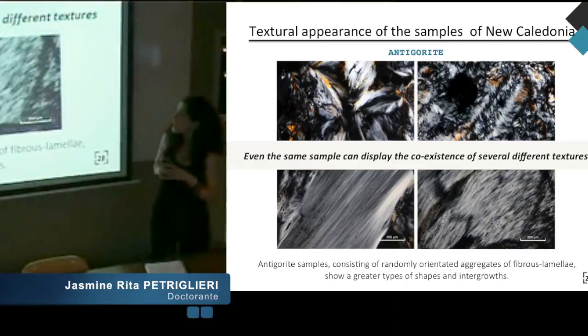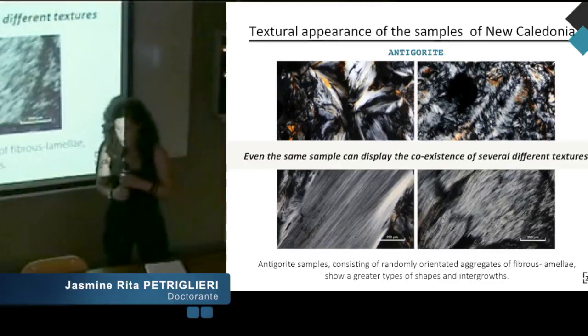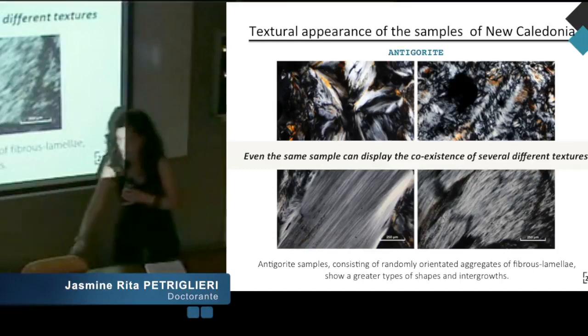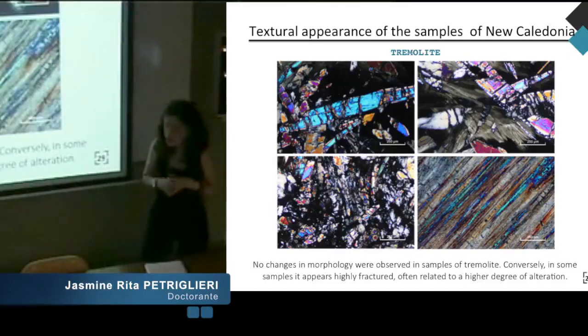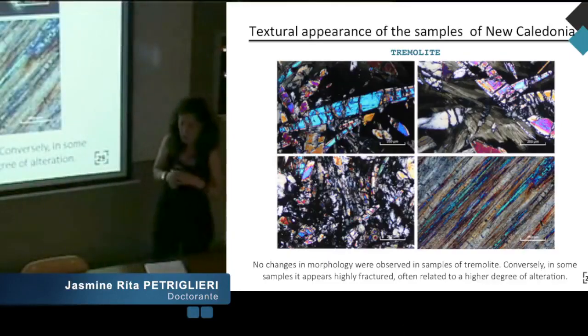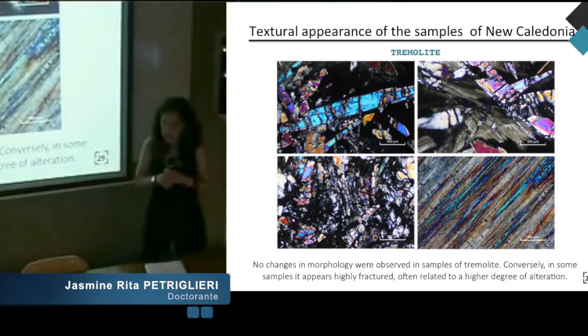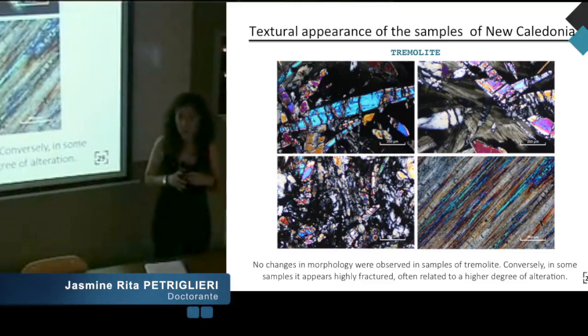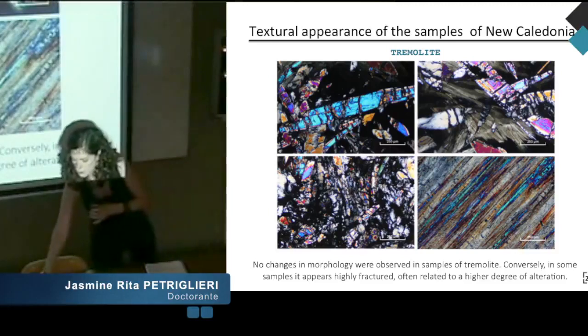And all these 4 textures were found in the same sample. It means that several kinds of texture can coexist in the same sample. Concerning tremolite, no great changes in morphology were observed, and just a few samples showed high fracturation, and that is often related to a higher degree of alteration.